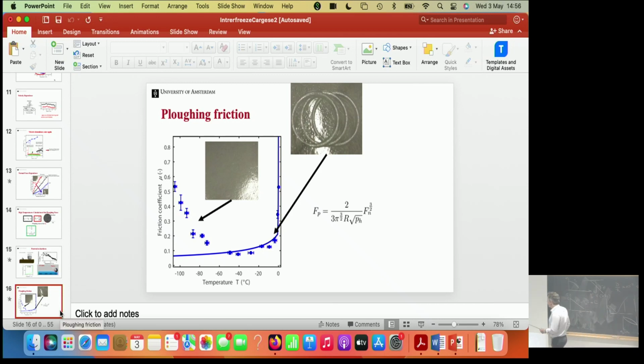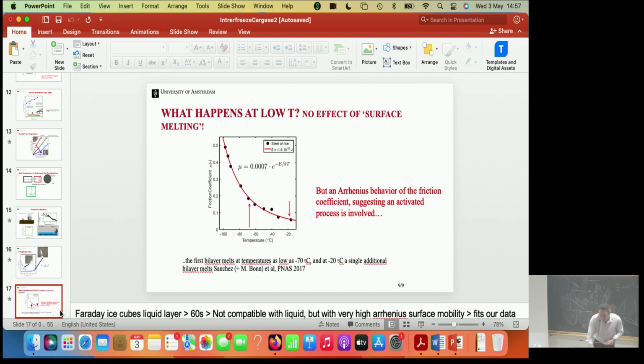And that is something we can actually directly compare to the data. So this is the plowing friction calculation without any adjustable parameters from the penetration hardness measurements, and you see that it gives a very good description of the data close to the melting temperature. Okay, we understood something. This is the reason why if you're walking over snow close to the freezing temperature, you won't actually slip. You will simply plow, just as the little sphere does, as you see here.